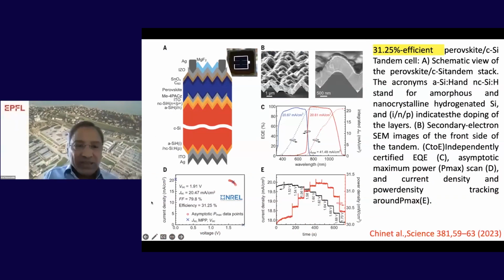Using this configuration, silicon and then the deposition of a conformal coating of the perovskite, this is work which I have taken from EPFL, Ballif's group. They have deposited the perovskite conformally on top of the silicon pyramids. They managed to get current matching of around 20.47 and 20.47 with efficiency reaching 31.25% using the silicon perovskite tandem configuration. This work is certified by NREL, and the efficiency certified was 31.25%, similar to what they measured in the lab.